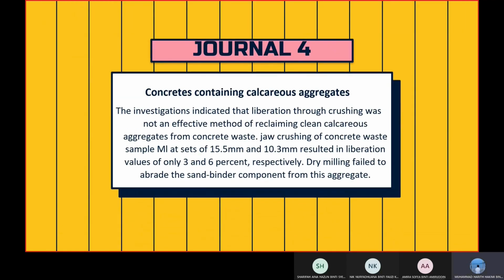So the next one is concrete containing calcareous aggregate. The investigation indicates that liberation through crushing was not an effective method of reclaiming clean calcareous aggregate from concrete waste, but the jaw crushing of a concrete waste sample M1 at sets of 15.5mm and 10.3mm resulted in liberation values of only 3 and 6% respectively. Dry milling failed to abrade the sand binder component from this aggregate.